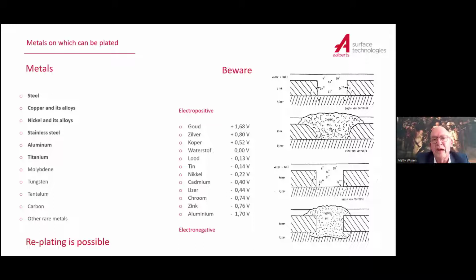On the right side is something which you have to be aware of, because we can plate all the metals which you have on the left side. But there's one risk here, one dangerous thing, which you see here on the right side. And that is when you plate a metal, you have to take into account its potential. For instance, if we have steel and we put copper on that, as you see in the galvanic series, copper is a nobler material. It has a positive potential of 0.52. Steel, however, has a negative one, 0.44.